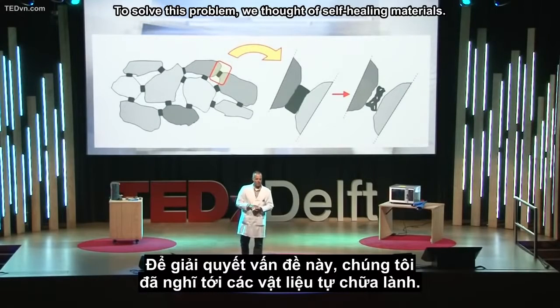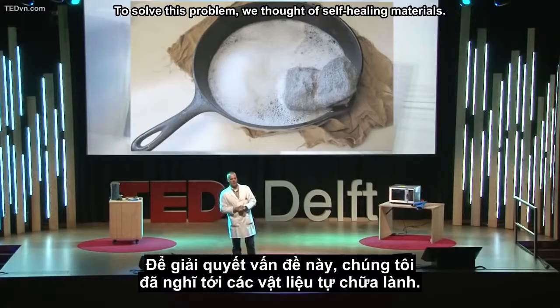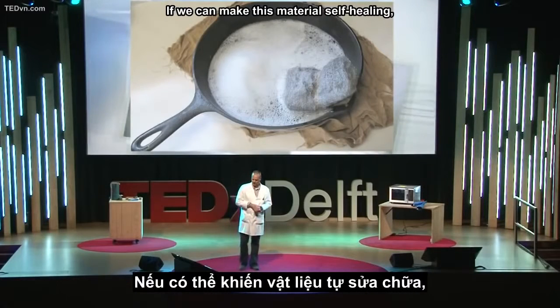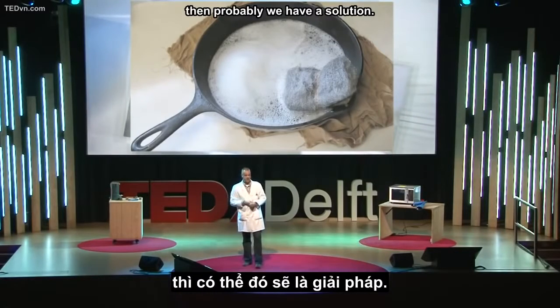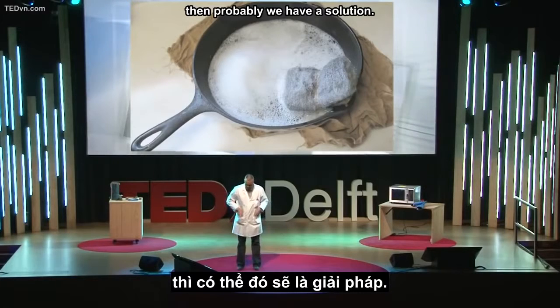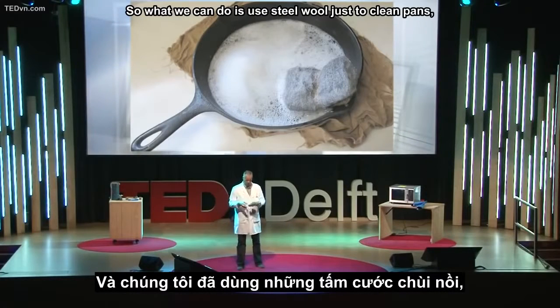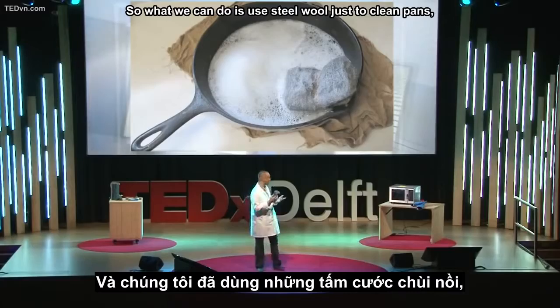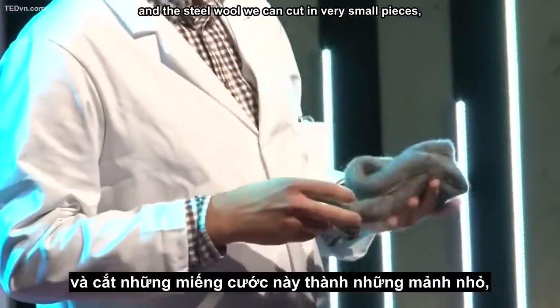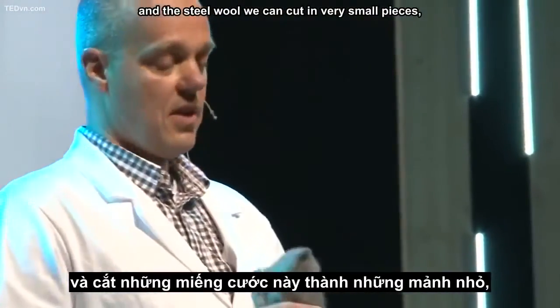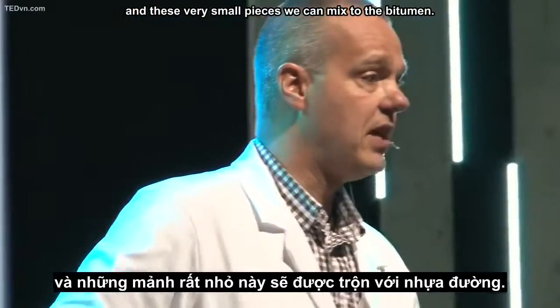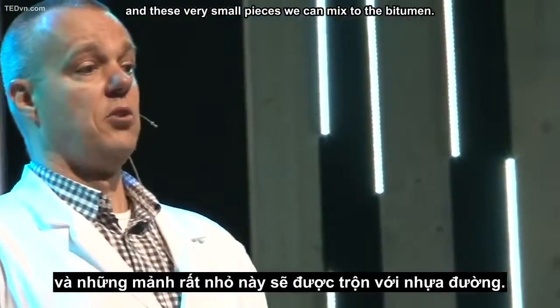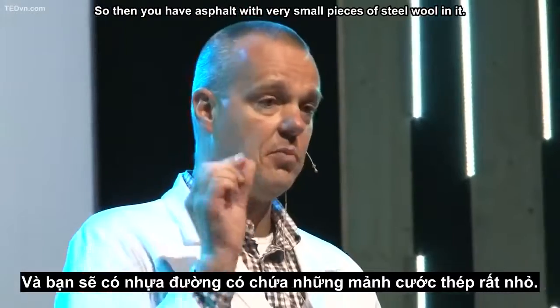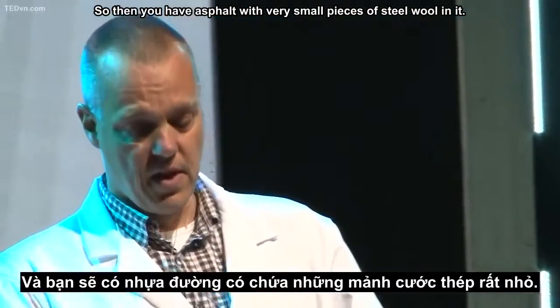To solve this problem, we use self-healing materials. If we can make this material self-healing, then probably we have a solution. So what we can do is use steel wool, just like the kind used to clean pans. The steel wool we can cut into very small pieces, and these very small pieces we can mix through the bitumen. So then you have asphalt with very small pieces of steel wool in it.